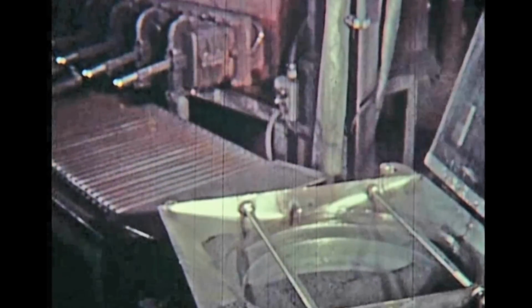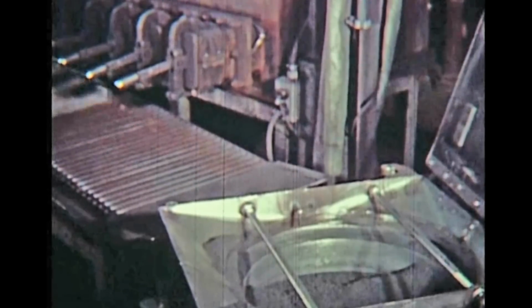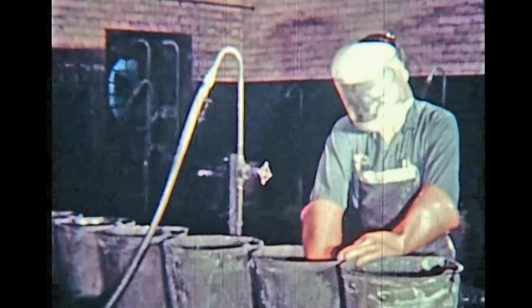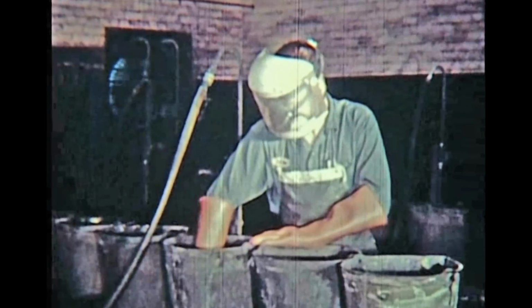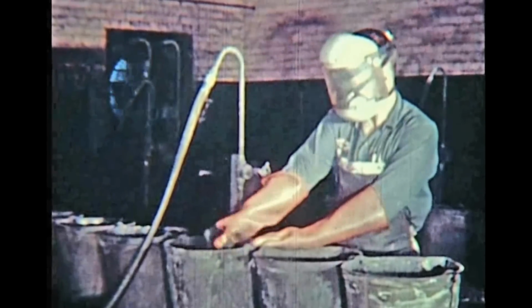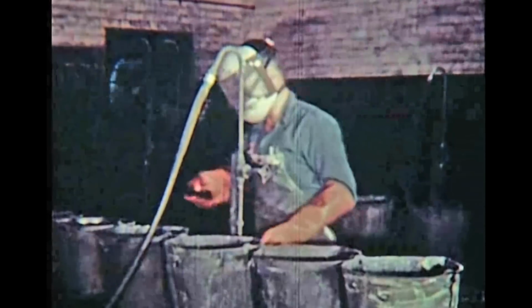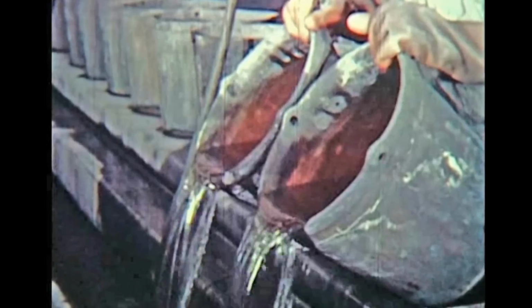The metal powder is sifted to remove agglomerates formed in reduction. The powder is placed in rubber buckets and hydrochloric and hydrofluoric acids to remove any excess dope which may have remained on the surface of the powder after reduction. The acid washing is followed by a thorough water rinse, after which the powder must be dried, sifted, and blended.